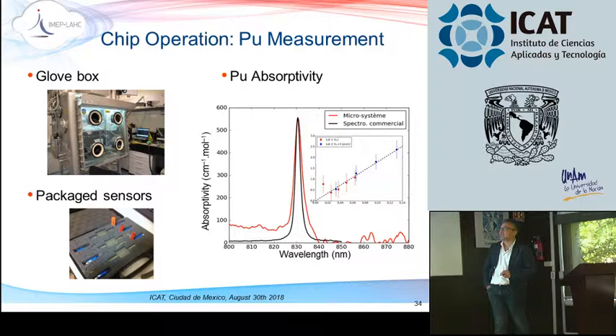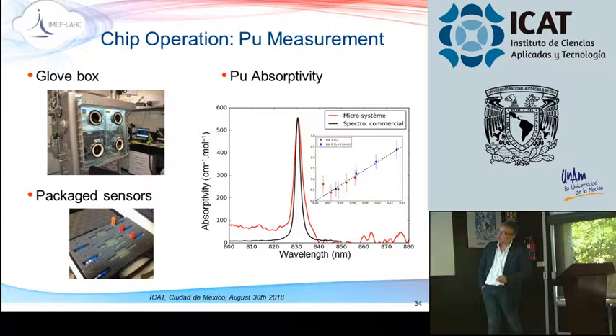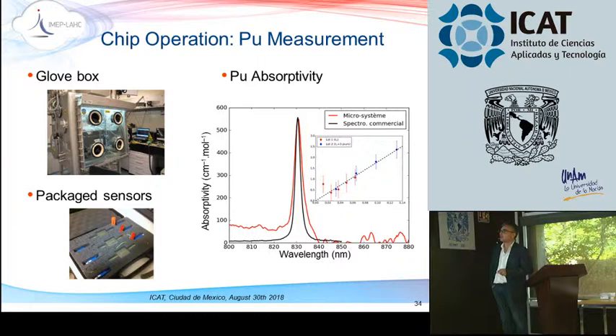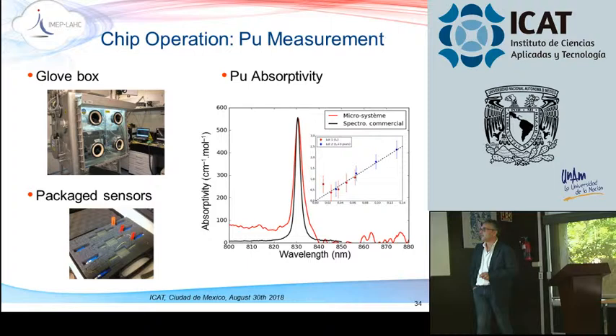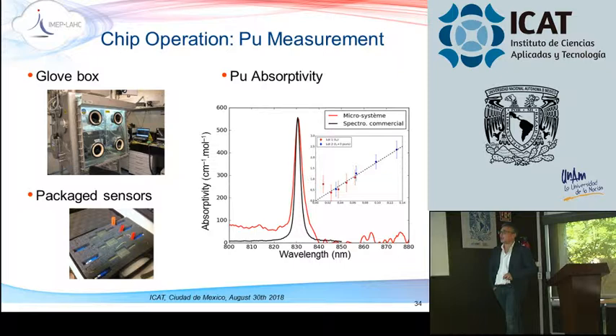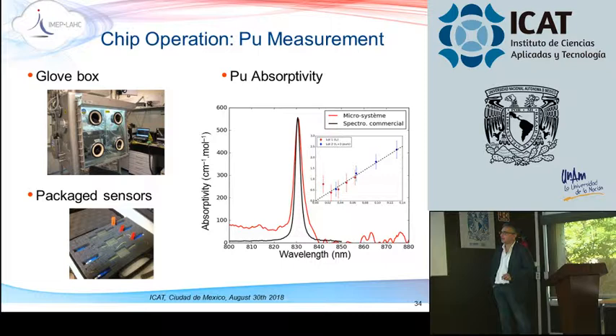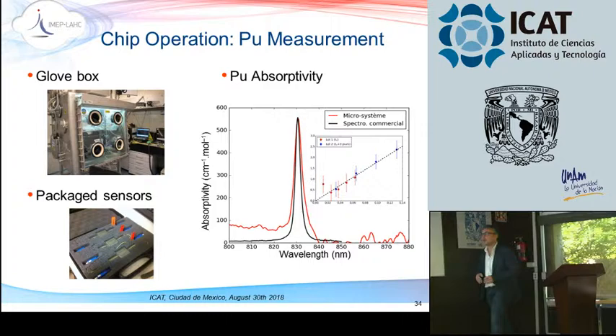And once we did this, we went into a nuclear environment, so things were installed inside that glove box, and all the optical parts like the source or the monochromator were outside the box. And these are the devices we provided, three devices that were fully packaged. And with this, plutonium was measured. You can see here in the inset the calibration line as a function of the concentration, and you see the absorptivity that has been measured with our device. It is in red, and in black you have the reference that we measured with commercial equipment. So we have good values, except here and here, where we have to slightly improve the noise of the measurement. However, we obtain this curve with only 21 microliters, so it's quite good.